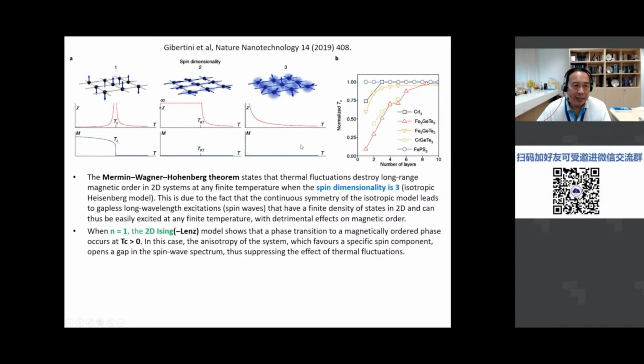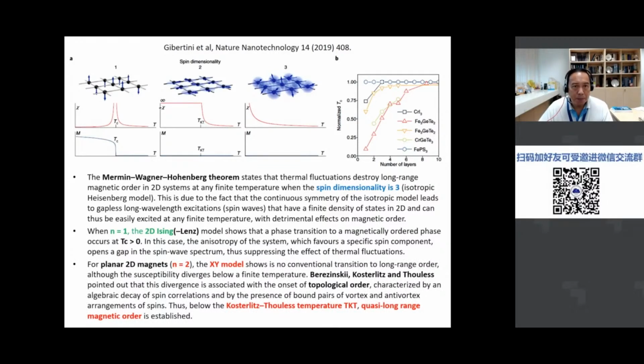On the other hand, spin dimensionality 1, this is the 2D Ising model where the spins can only point up and down, right? You can see a phase transition to a magnetically ordered phase at a finite Curie temperature Tc, as shown here, right? That's because a gap is open in the spin wave spectrum and it suppresses the effect of thermal fluctuations. So in the n equals 2 case, which is the case of the planar 2D magnets as shown, the model here is known as the XY model.